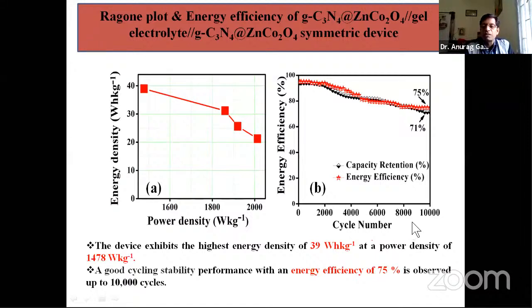As compared to batteries, that is good, because battery performance generally goes down after up to 2,000 cycles. But here, up to 10,000 cycles, they retain up to 75% energy efficiency. So that is also quite good. The only thing is that it is now improved up to 39 watt-hour per kilogram, but we have to improve this towards the battery range, at least 100 or 150 watt-hour per kilogram. Then we can think of replacing batteries with supercapacitors.